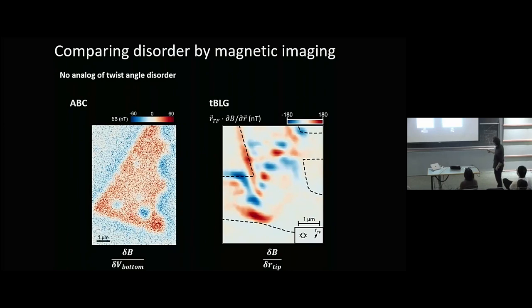Whereas twisted bilayer graphene, actually the scale bar here is about double, but it's extremely non-uniform. And we know that this comes from twist angle disorder and the fact that twisted bilayer graphene is not a structural ground state. It's not even a metastable state. It's just unstable. So you're trying to quench whatever strain happens to be there during your fabrication process in a particular way. Okay, so there's no analog of twist angle disorder here because there's no Moiré to be disordered and there's no twist angle to worry about. Okay, and that's really quite useful, as I'll show you.